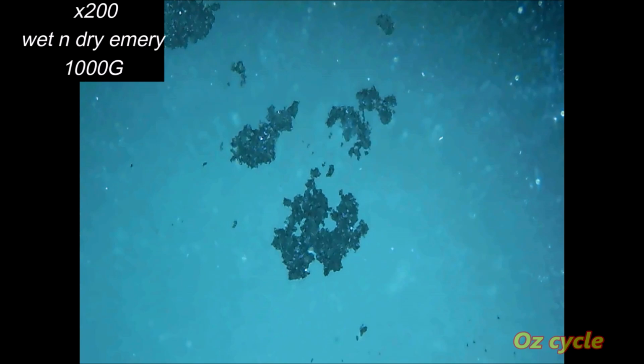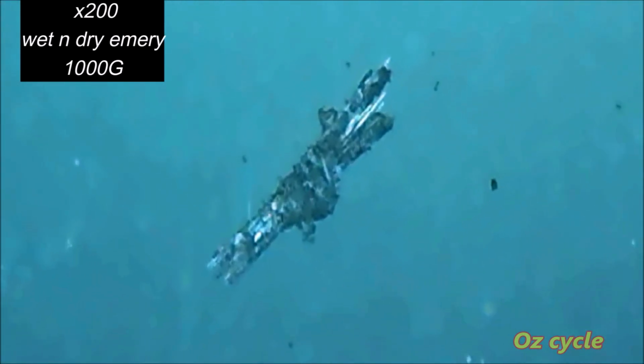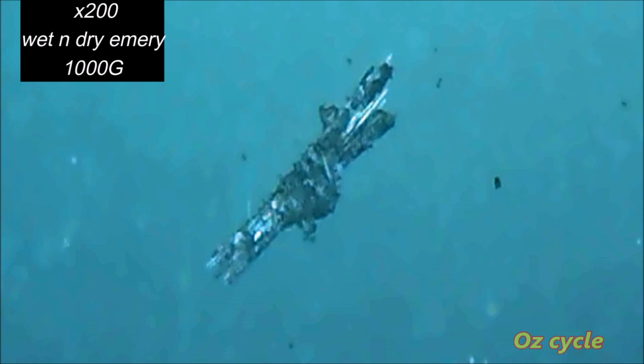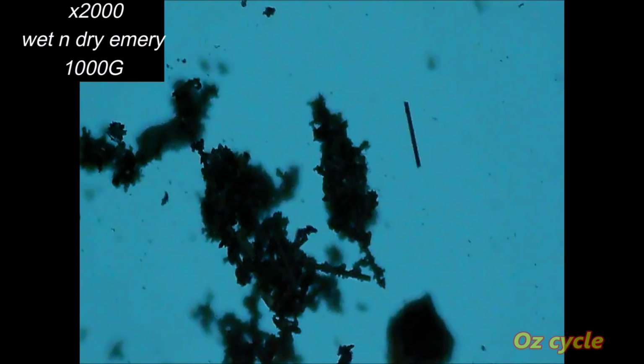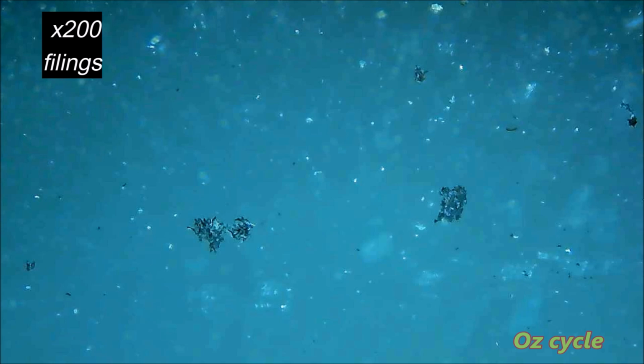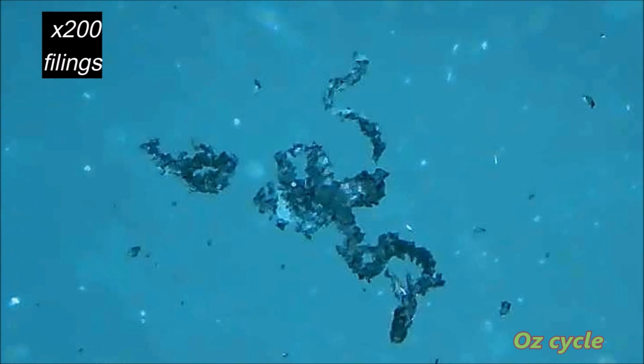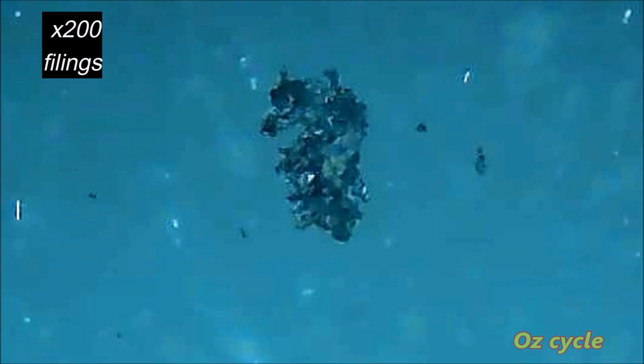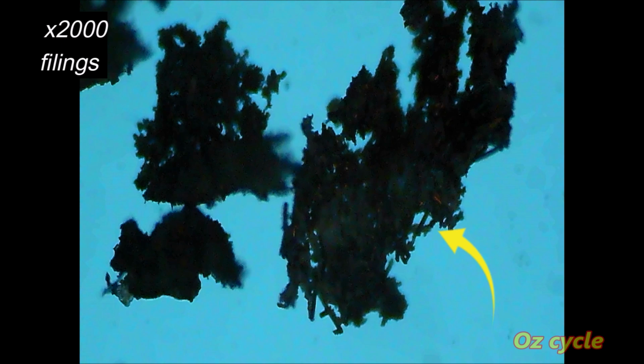1000 grit emery and the splinters are almost undetectable. It's because the abrasion is so fine. Over to a different picture, different cluster, there you can see sticking out there some carbon splinters. 2000 magnification and we can see a few splinters sticking out of the clusters there and one splinter on its own. The filings, can't see any carbon fibre splinters, even zooming in with another picture, still can't see any. However, with the 2000 magnification we can definitely see the carbon splinters, but they're well within the clusters.